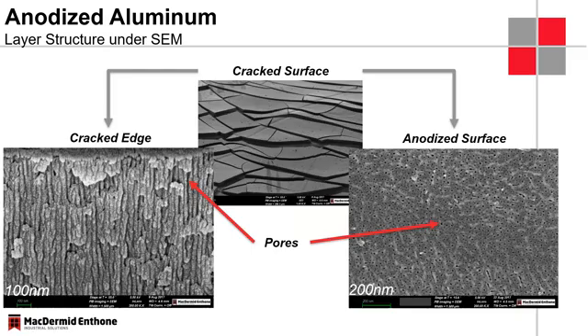If we look at the anodized surface from the top, like the bird's eye view, that's the picture here on the right, and we see all these little black dots. Every one of these black dots is an anodized pore, and these pores are extremely small. They range from 5 to 15, maybe 20 nanometers. So extremely small, but there's a vast amount of these little pores on an anodized surface.